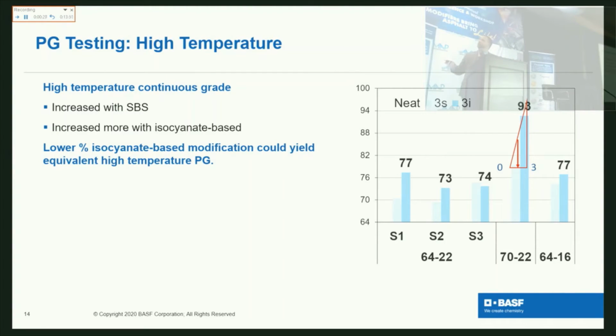In this case, we found that a lower percent isocyanate-based modification could get an increase at least equivalent or better than just using a straight SBS modification. I don't know if you guys can see the light blue colors there, that's the SBS modification.